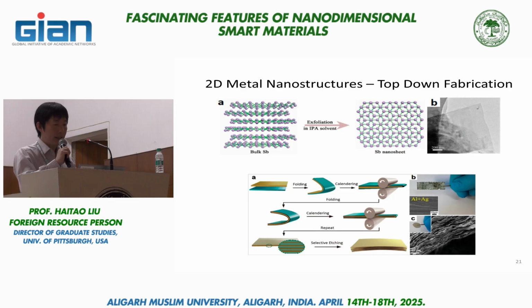Another approach is very mechanical in nature. You start with bulk metal. You can add some kind of sacrificial layer, and you simply compress it mechanically, layer after layer. So you do mechanical pressing, fold it, press it again, fold it, press again. Gold, for example, has very good flexibility, and you can do this to the point that each layer is a couple of nanometers thick.